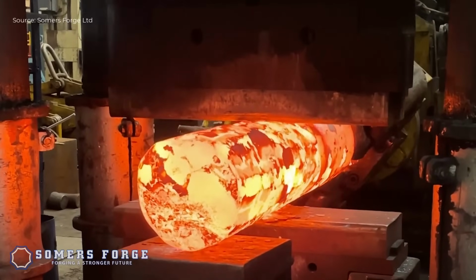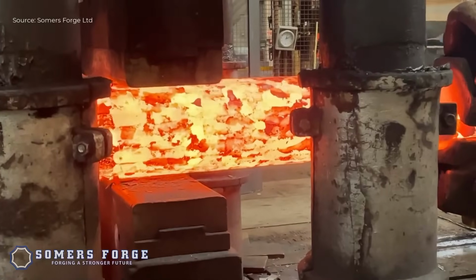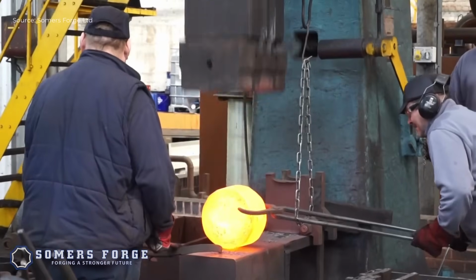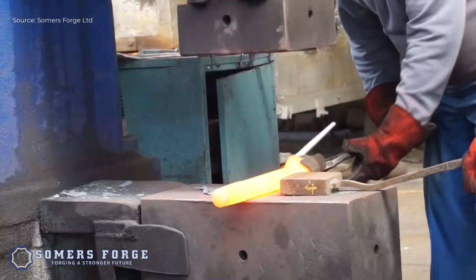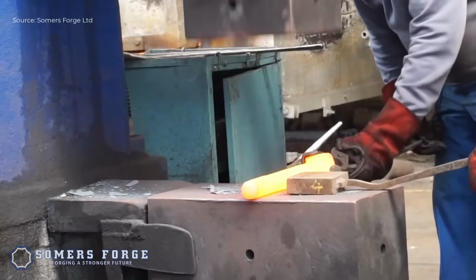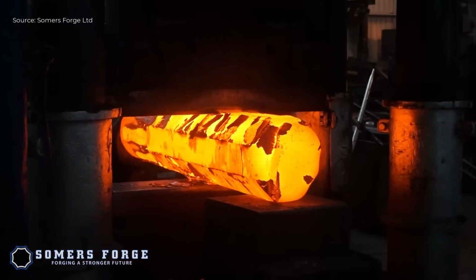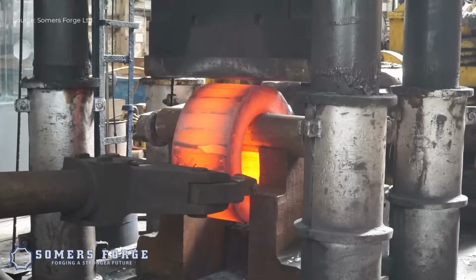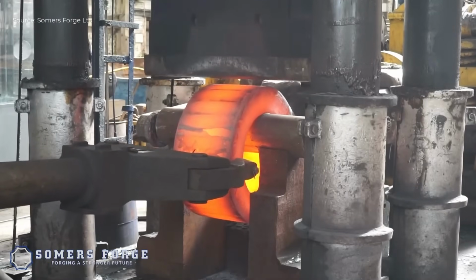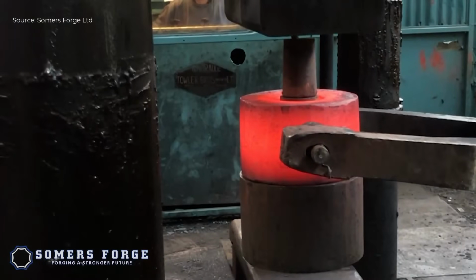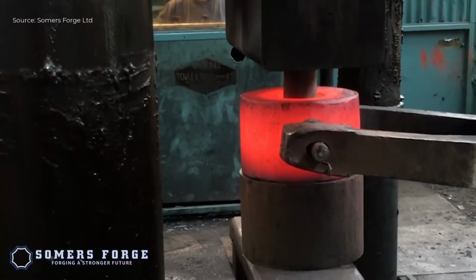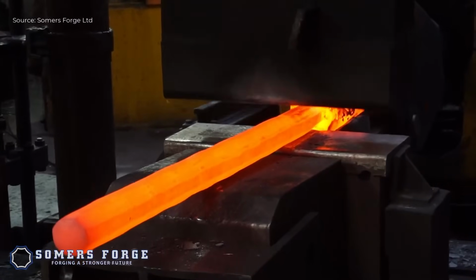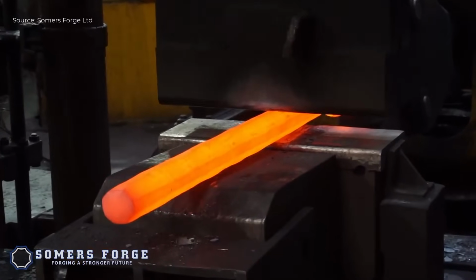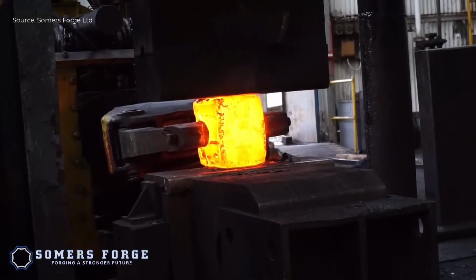The 1000-weight and 3500-weight hammers deliver fast, repeated blows to shape small to medium billets. The 500-ton press forges larger sections with steady force, enhancing density. The 1,200-ton press handles massive components, applying deep, controlled pressure for refined grain structure and improved mechanical properties in critical forged parts.